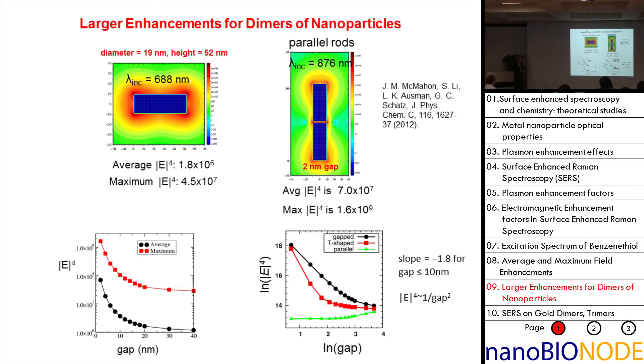It turns out that if you take a rod and put two of them together with a small gap — like a two nanometer gap — you get an E⁴ which is nearly 10⁸. That says that what you really want to focus on in SERS is these small gaps — the electromagnetic hotspots — because that can completely dominate the Raman intensity. When you look at E⁴ as a function of gap size, it just gets bigger and bigger as you go to smaller gaps. On a log-log plot, it's more or less linear, and you get a 1/gap² dependence of E⁴. So that's pretty amazing — you want to make that gap as small as you possibly can.